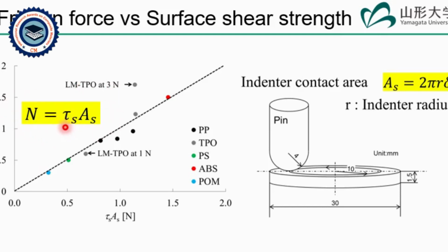In that equation, A s denotes the indenter contact area. Assuming that the contact area shape is spherical, the right equation is obtained. Therein, R represents the indenter radius, and delta denotes the indentation depth, which is divided into an elastic deformation component and a plastic deformation component.